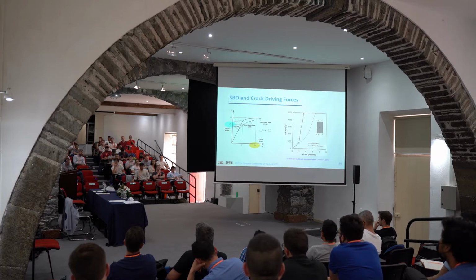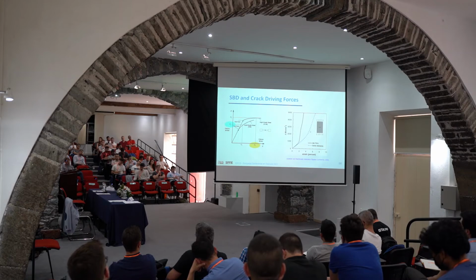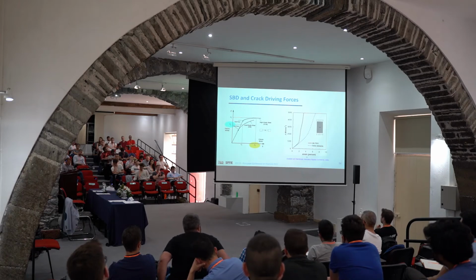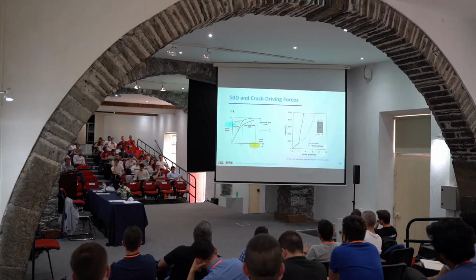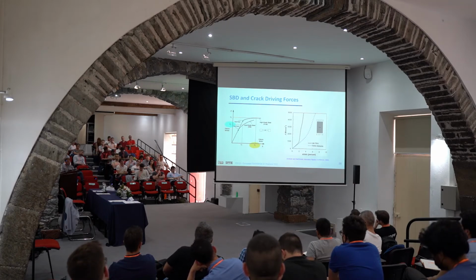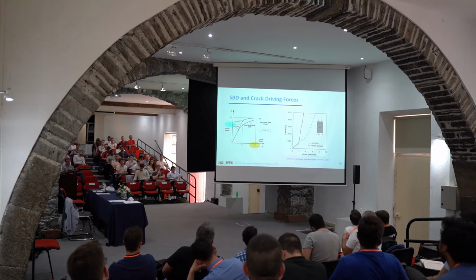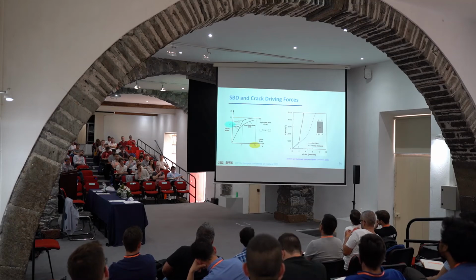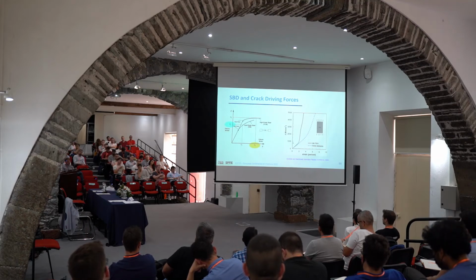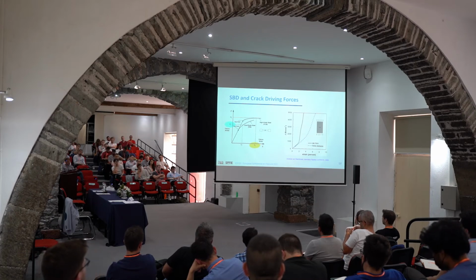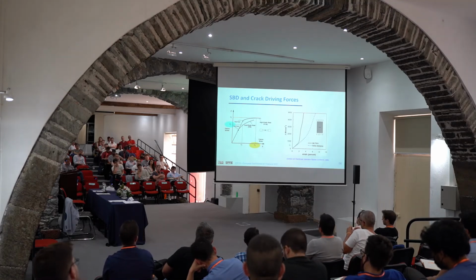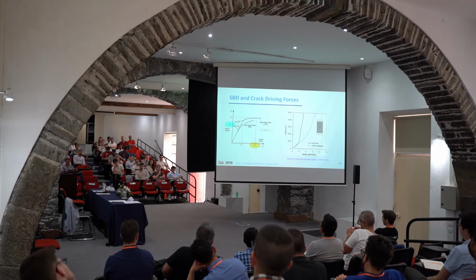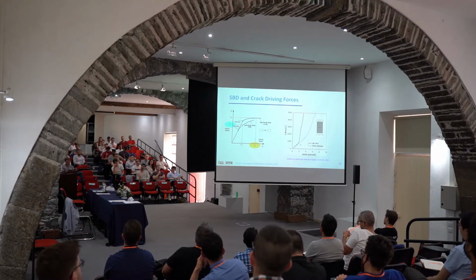So usually, and here it shows the whole story. This is J. This is for a center cracked panel. I'm not sure which material it is because I just took it from this paper, so they didn't mention which material it is, but I guess it's a medium strength material. You can see here, this is the J versus strain. If you use BS 7910 to estimate the J integral, you have this solid curve. If you conduct a nonlinear, large strain finite element analysis, all that stuff that you know, you are going to have a different relationship between J and strain. And that's very important for the assessment.